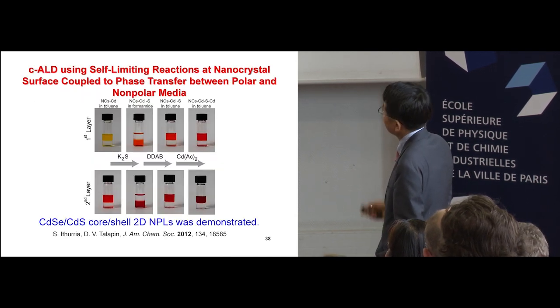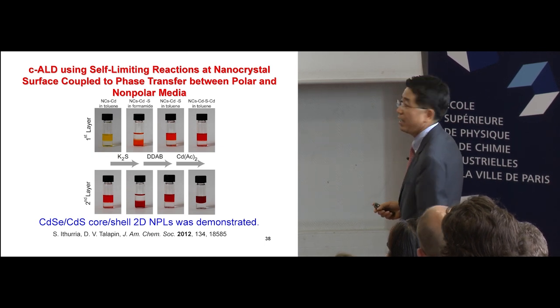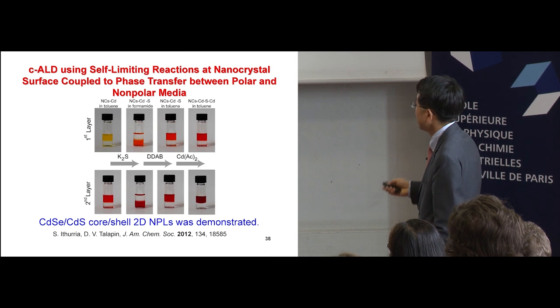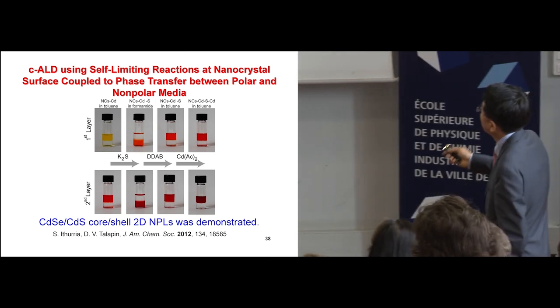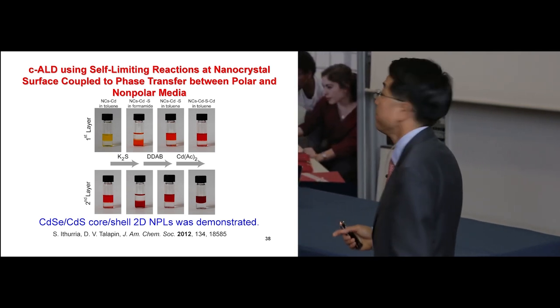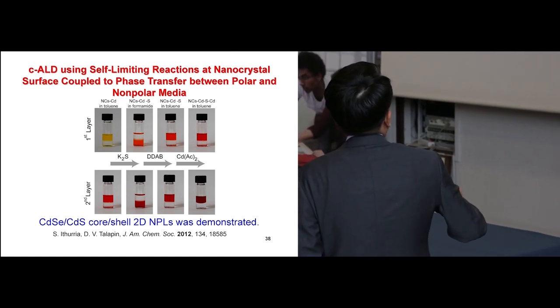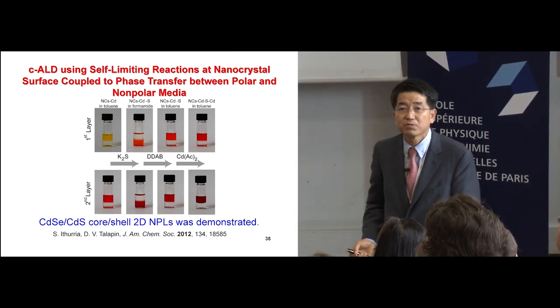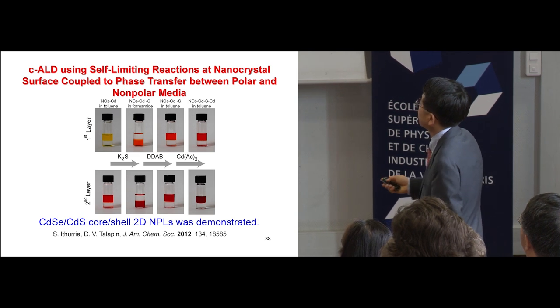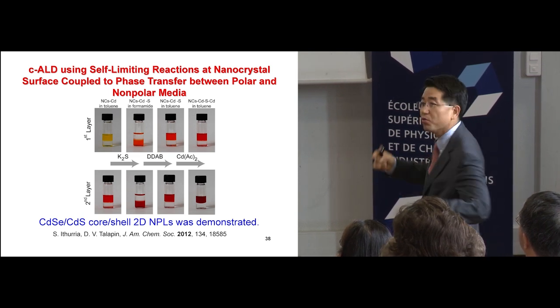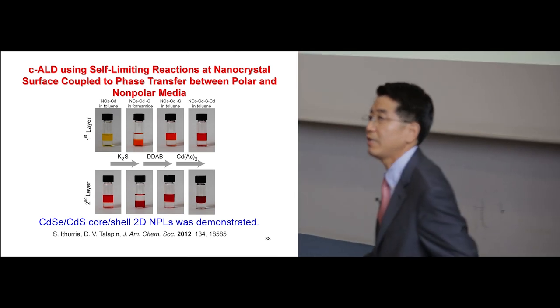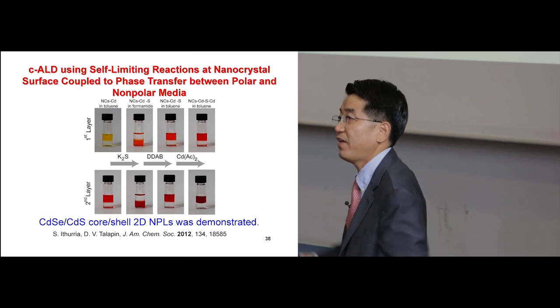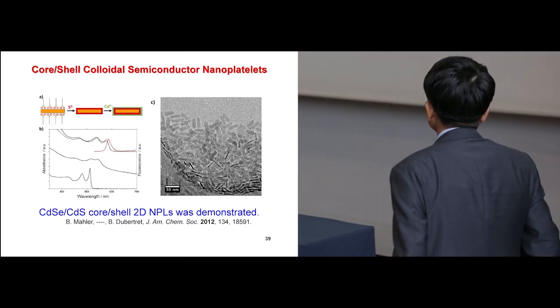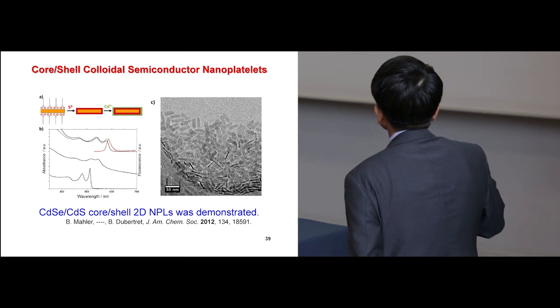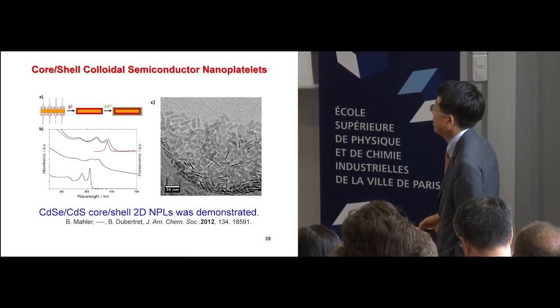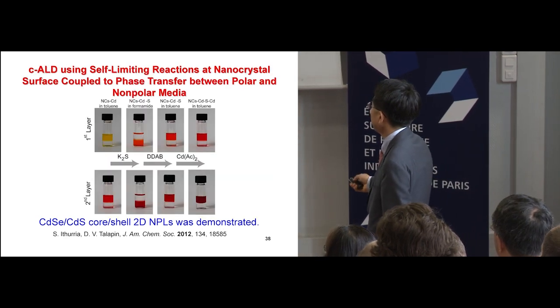Then, at a very similar time, Dmitri Talapin's group and Benoit Dubertret's group made core-shell structures. First, they make a CdSe core. In this case, this is the Talapin paper, and these two papers were published back-to-back in JACS. For the first time, the CdSe is formed, and on the surface they also decorate a CdS sulfide layer on top, to make core-shell nanoplate structures. And very similar materials were also reported by Benoit's group, as you can see, 85 and 91.